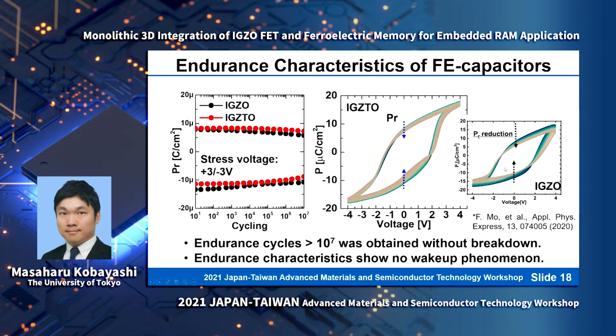And we also studied the reliability of this fabricated capacitor. The biggest advantage with this IGZO capping or IGZTO capping is that we can achieve very stable endurance characteristics. In the previous report, with the IGZO capping ferroelectric capacitor, we reported so-called wake-up-free, very stable endurance characteristics like this. This time, we got almost the same results with IGZTO capping. As you can see, there's almost no unstable wake-up phenomenon with the IGZTO capping. So the endurance characteristics can be largely improved by the IGZO or IGZTO material capping.